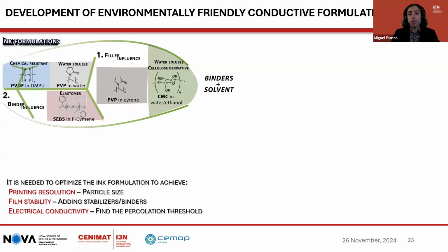To keep the ink stable and avoid agglomeration, or to improve adhesion, or even to tune surface tension, or avoid foaming that can happen in screen printing, it is important to add stabilizers in the form of polymers or small molecules.